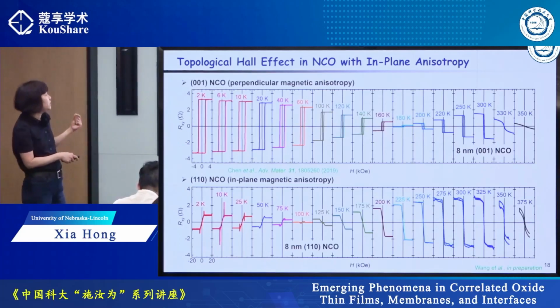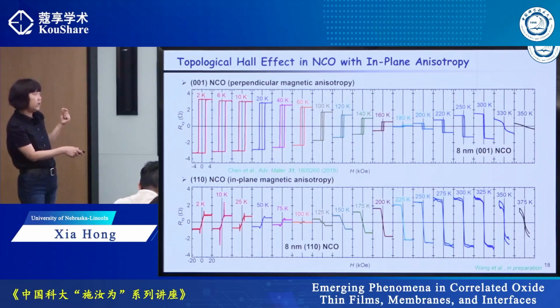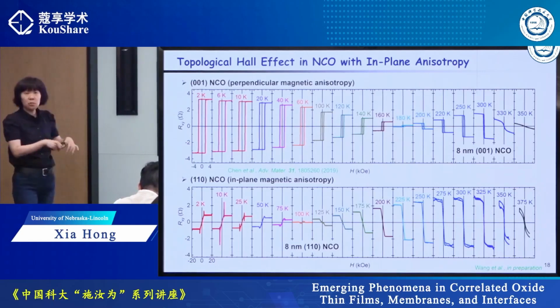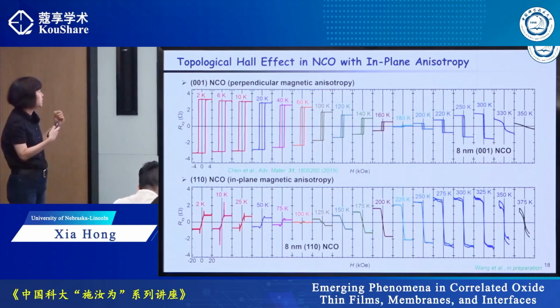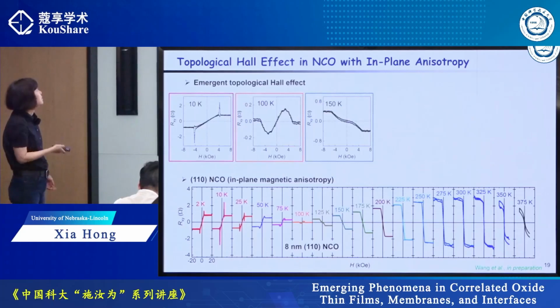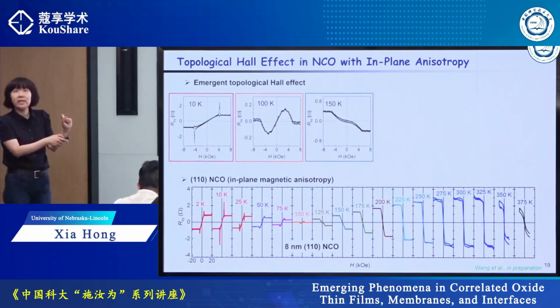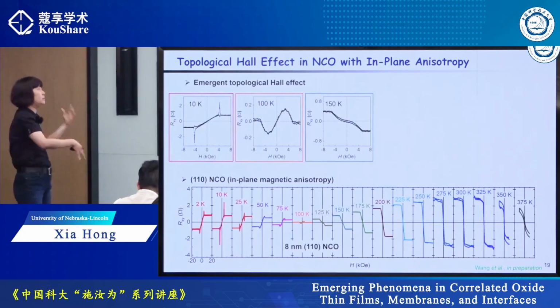But what is interesting is that on top of a normal Hall effect, which is basically a linear one, and the anomalous Hall effect, you also have these small wiggles that are associated with the topological Hall effect. This is probably most pronounced at 100K because this is where the anomalous Hall effect is about to change sign and becomes 0. And you can see this.